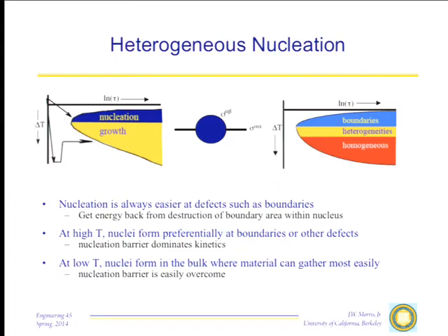Nucleation is easy, growth is a problem. And as a consequence down here, in, for example, a polygranular body, you'll get a shower of nuclei more or less everywhere through the volume. So if I get my transformation, if it's a precipitation reaction, for example, and I get it to happen down here, then I can get precipitates more or less uniformly dispersed through the bulk. That's what I must have if I'm going to use an array of precipitates, for example, to harden the material. So this behavior is also important.